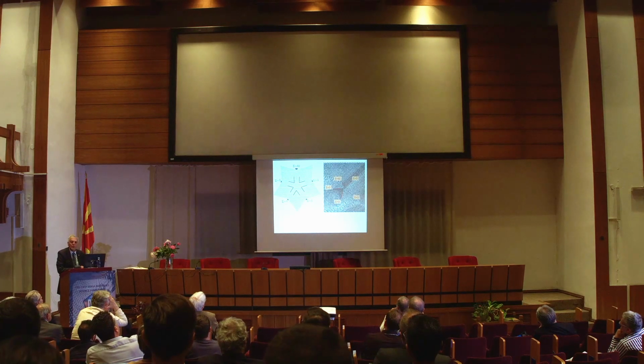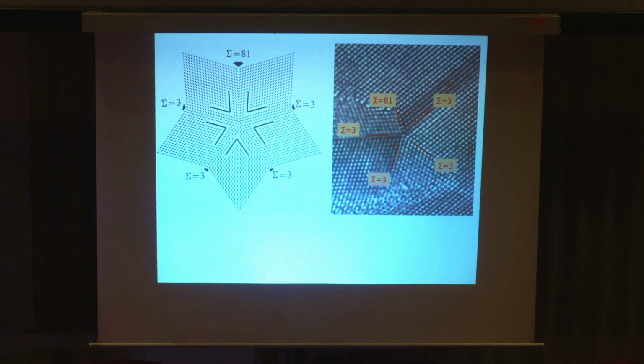Okay, this is twins. These are twins in diamond, and on the left you see just a computer model of the same. You see the sigma notations, forget about the sigma notations, they belong to another chapter. But you can see there are 5 twins here, and the red lines mark the twin boundaries. This is a part of the crystal, and the relationship between 2 adjoining twins is something like that. We call them twins because they look like twins. I have 2 grandchildren that are twins. So you see that there are 5 of them.